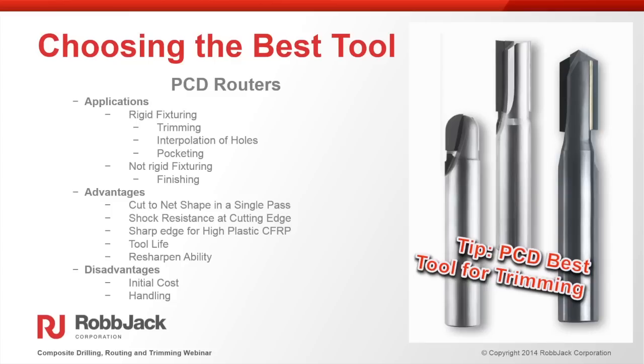One of the main causes of PCD failure is misapplying the tool. A lot of times when we run into a failure with PCD, we find out that the customer is using it the same way they would use a burr-style carbide tool. They run at really high RPM, very slow feed rate, take lighter cuts, multiple passes, whereas the advantage with the PCD, and the video that we're going to show, is that typically we can cut right to net shape in one single pass, with no need to rough the part and finish the part or use multiple tools. A lot of times when we do this trimming operation, we're able to use the tool full depth, one pass, right to size in one shot.